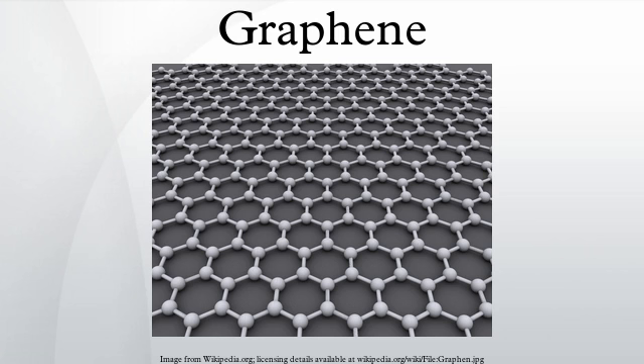Graphene sheets in solid form usually show evidence in diffraction for graphite's layering. This is true of some single-walled nanostructures. However, unlayered graphene with only rings has been found in the core of pre-solar graphite onions. TEM studies show faceting at defects in flat graphene sheets and suggest a role for two-dimensional crystallization from a melt. Graphene can self-repair holes in its sheets, when exposed to molecules containing carbon, such as hydrocarbons. Bombarded with pure carbon atoms, the atoms perfectly align into hexagons, completely filling the holes.